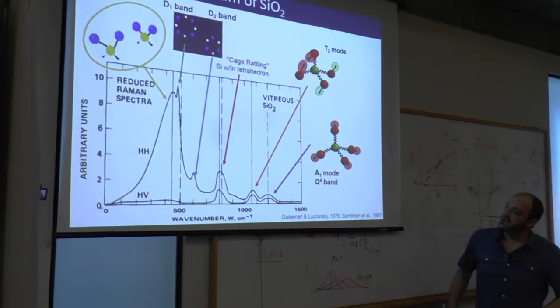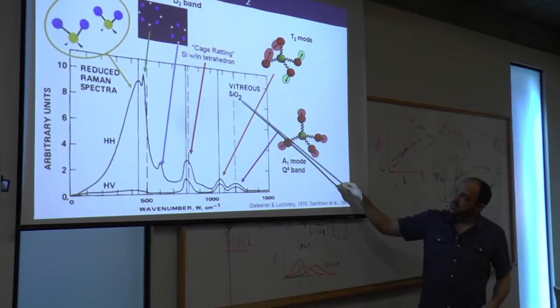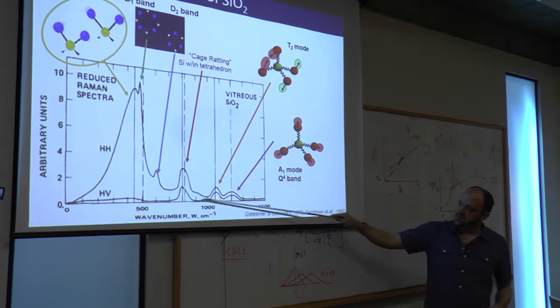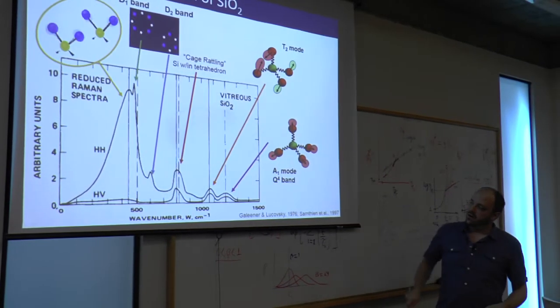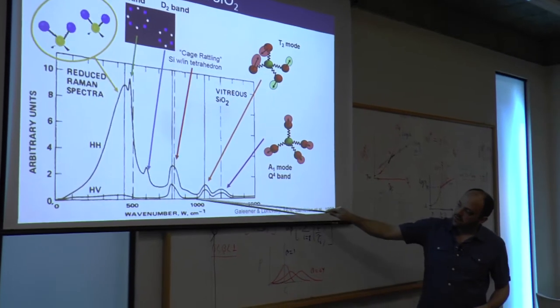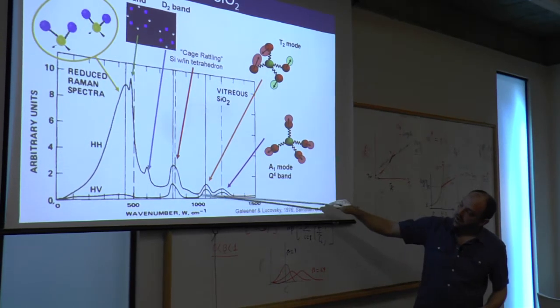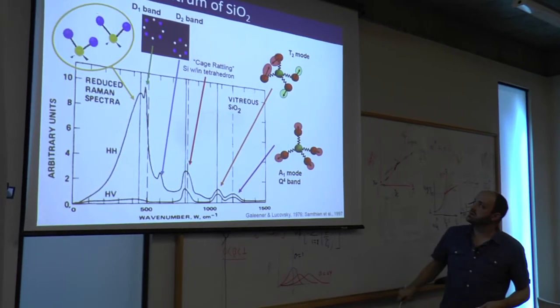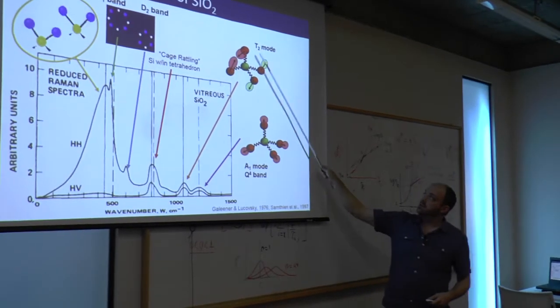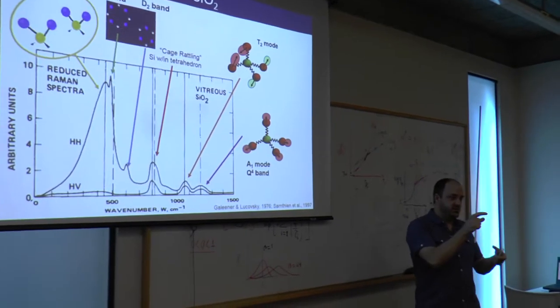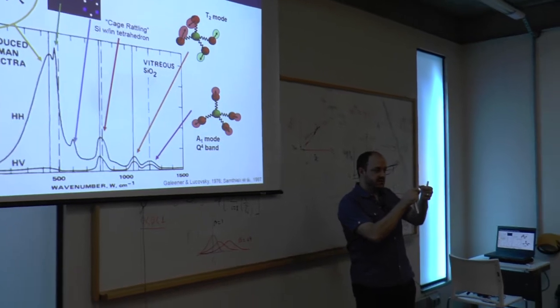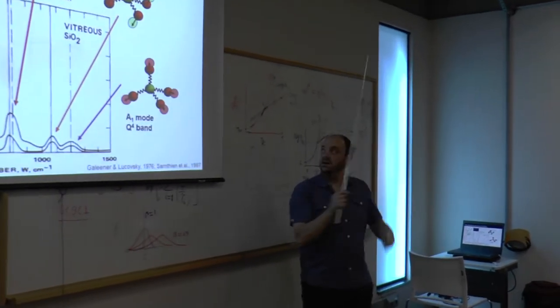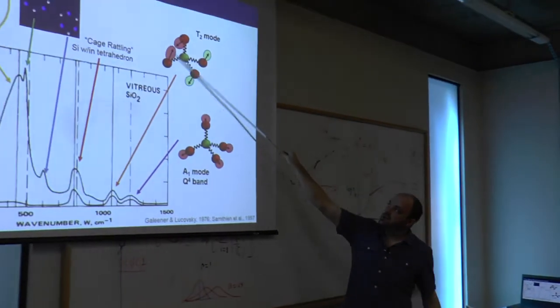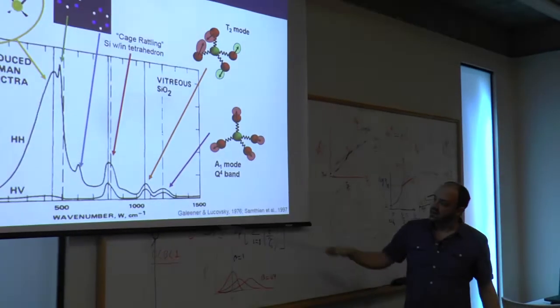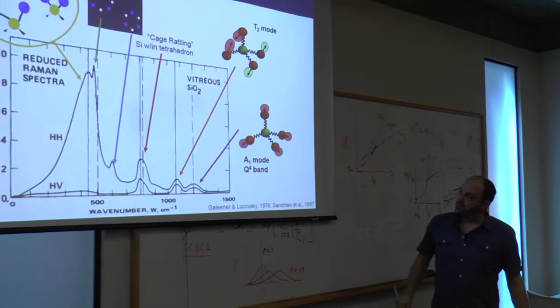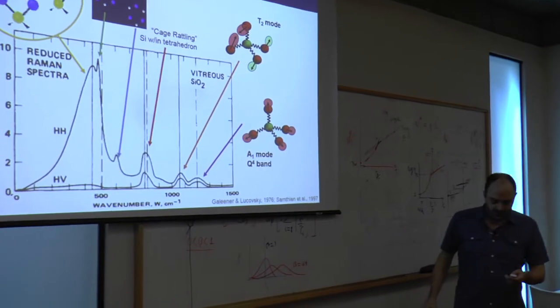We have this cage rattling vibration, and for pure silica, we have these two small bumps, which are seen here around 1080 and around 1200 or so. These belong to the T2 mode, where you have pinching of two parts of the tetrahedron and an extension of the other. So you have sort of a motion like this. As two go away from each other, two go towards each other in the tetrahedron. And then a symmetric vibration of the Q4 band here.